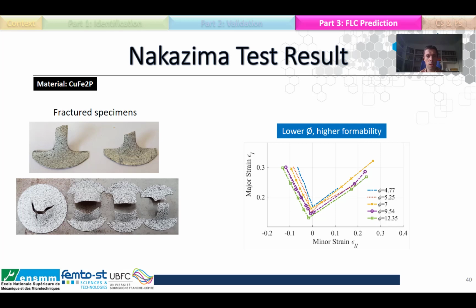We can note that the lower the phi, so the lower the number of grains in the thickness, the higher the formability. In order to obtain this forming limit curve, we were obliged to follow step by step the ISO 12004, and we developed our own algorithm under MATLAB. Because of the size of our sheet, we cannot use the automatic forming limit curve algorithm in the Aramis